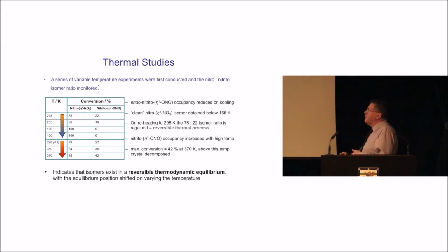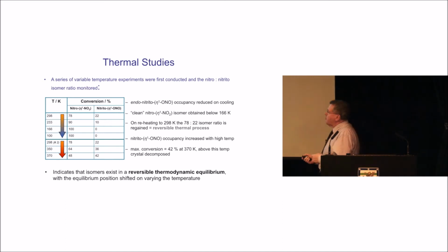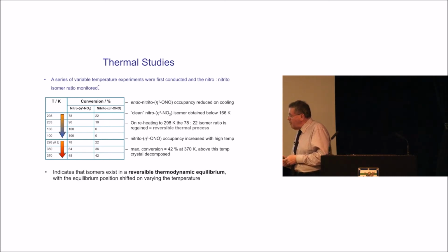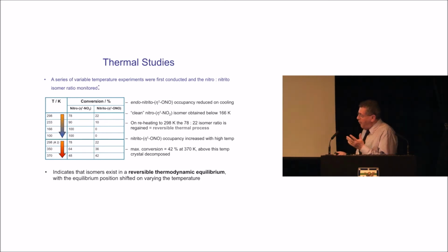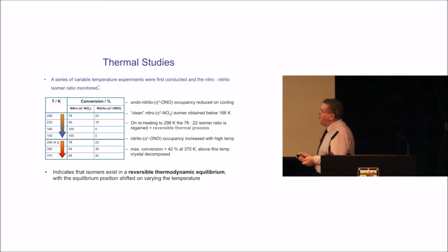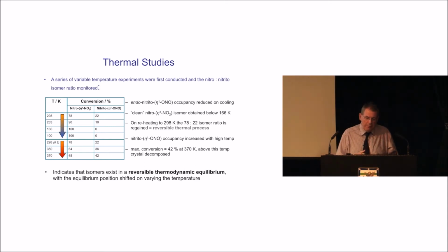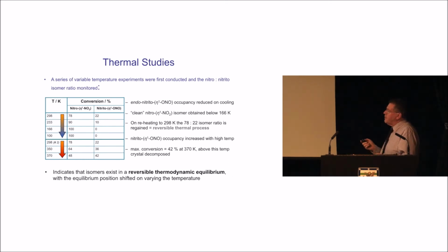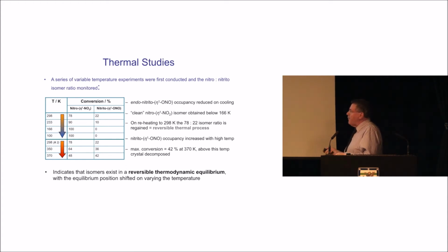If you cool the crystal down, below 166 K, you get 100% of the N-bound form, so a clean N form. And you can then also warm it back up, and you go back to the 78-22%, again without particular loss of crystallinity. And you can even take it higher, go to 42% at 370 K, above which it decays. So we have that equilibrium.